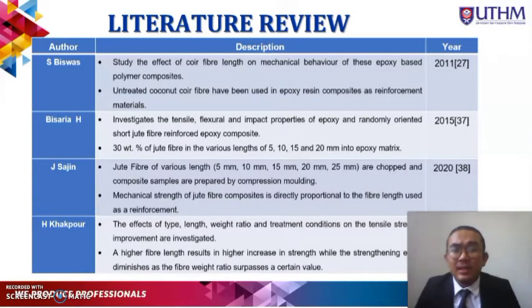This slide shows the literature review. Firstly, Biswas has conducted a study on the effect of coir fiber length on mechanical behavior of epoxy-based polymer composite. Untreated coconut fiber has been used in epoxy resin composite as reinforcement material. Next, another study investigated the tensile, flexural, and impact properties of epoxy and randomly oriented short jute fiber reinforced epoxy composite, with 30% weightage of jute fiber in various lengths of 5, 10, 15, and 20 mm in the epoxy matrix.